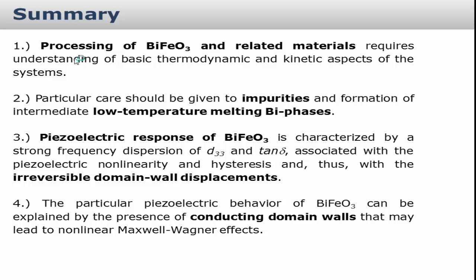In the processing of BiFeO3, one should take care about impurities, about liquid phases, how powders react, and so on. And then I tried also to show that BiFeO3 has a specific piezoelectric response, very different from other materials that we know well, for example PZT, and it looks like it is related to these conductive domain walls which are present in this material.